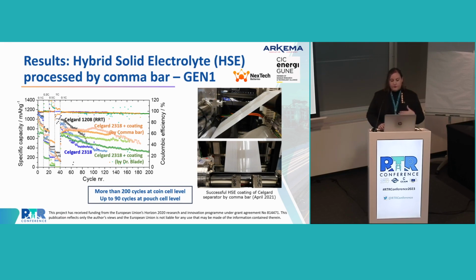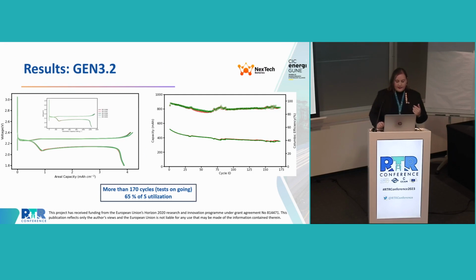Now I am able to show you the latest results that we've got. This is at pouch cell level, evaluated with 65% sulfur utilization and the upscaled hybrid solid electrolyte. Here, you can see that we are able to reach more than 170 cycles, and these tests are ongoing. So the battery is not dead. We will see how far we get with this new generation of battery.